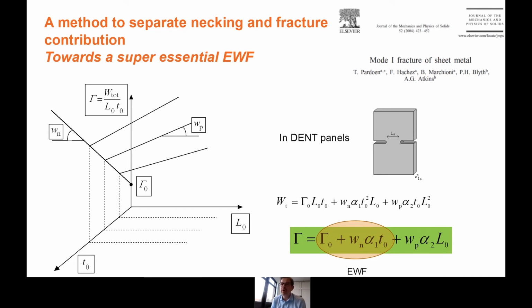So exactly as what we do for the essential work of fracture, where we try to separate the plasticity, extrinsic plasticity, and the work in the fracture process zone. Now we take the work in the fracture process zone, and we try to separate the necking work and a more essential, a super essential work, which we call gamma 0. And in order to do that, we developed a double regression approach, where basically you do tests at different ligament lengths and then you do tests at different thicknesses in order to separate the gamma 0 from the work of necking.